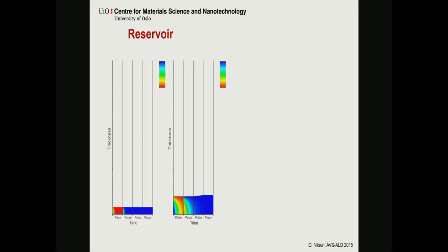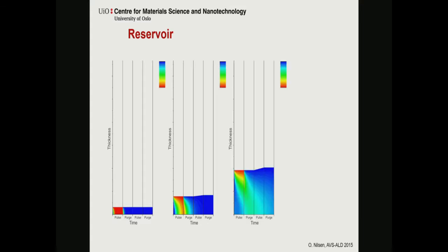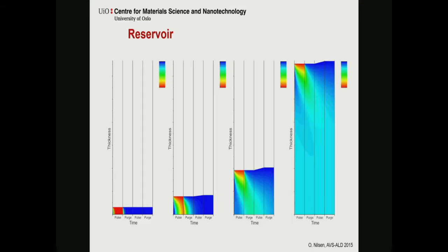And that grows more or less like a bulk saturation. So it's a reservoir that is being consumed, and you increase the growth. You can continue with this, and eventually you get a steady state, where you don't have enough time for all of this to empty, but you have a constant concentration in here, so your additional growth is going to be constant.